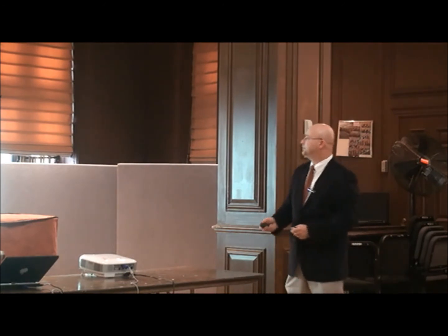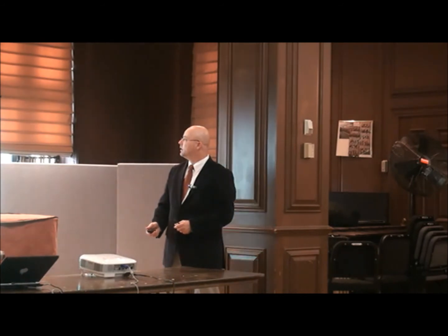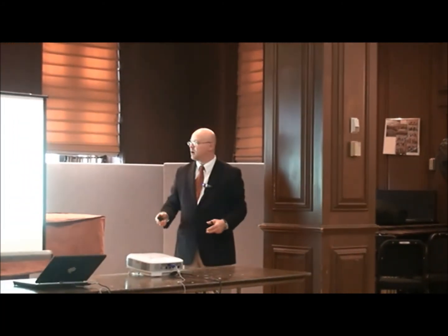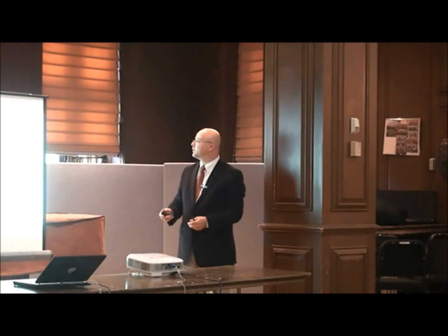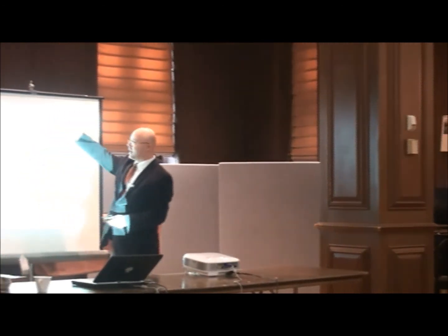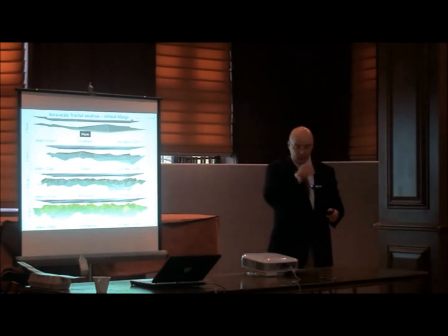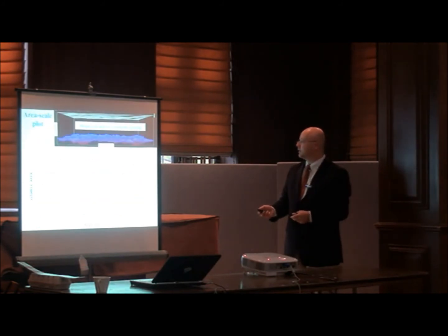So I'll talk a little bit about the area scale fractal analysis. We looked just at the length scale analysis before. At the area scale, we can do something similar to that Richardson tiling, but on a 3D topography instead of on the 2D profile of the surface. We take little triangular tiles, and we see how many of these triangular tiles we can fit on the surface. We calculate the area of one triangle, so each triangle has the same area. The shape is allowed to vary just a little bit. Again, you add up the total area of all the triangles and divide that by the projected area onto a flat plane, and you've got a relative area plot now instead of the relative length plot.